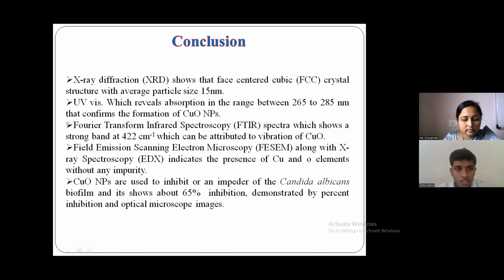Then these are the conclusions. The XRD plot shows the face-centered cubic crystal structure with an average particle size of 15 nanometers. And UV-visible reveals the absorption in the range between 265 to 285 nanometers. That confirms the formation of copper oxide nanoparticles. Then FTIR shows a strong band at 422 cm⁻¹, which can be attributed to the vibration of copper oxide.